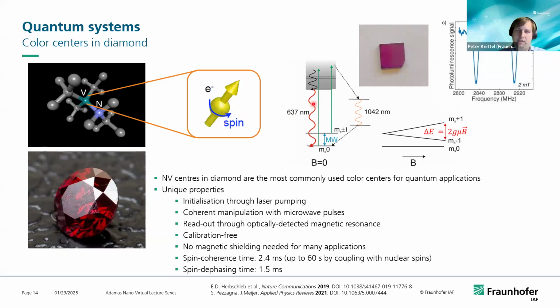So this is shown here in this plot. If we shine green light on a diamond that contains NVs, we're actively pumping it into the MS0 state, because if it goes from the MS ±1 spin state into the excited state, it will go over via intersystem crossing into this non-radiative path and go back into an MS0 state instead of the MS ±1 state, and that allows us to initialize the diamond in this MS0 state.